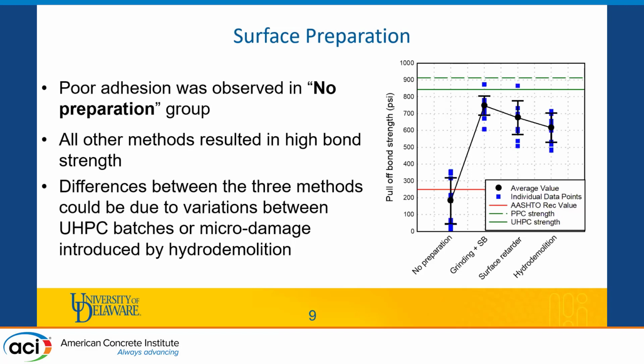With all the other methods, we see that they have good bond strength, and the average is decreasing from approximately 700 to 650 psi across all the methods. And this decrease in strength is probably also due to the different batch of UHPC for all these experiments. We can see that the bond strength for the hydrodemolition is lower, and that could be due to the high pressure water used in this method, probably weakening the specimens.